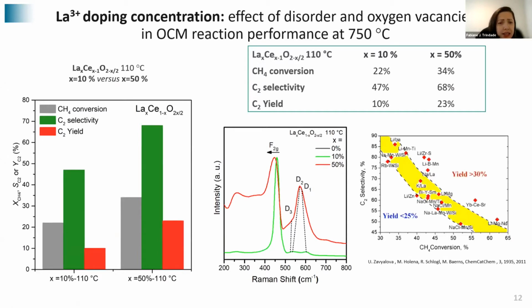And as I said, this OCM reaction is still not commercialized. We need 30% yield, and in these first tests we made, we achieved 23%. So that is really good. It is up to most of the work published in the literature.